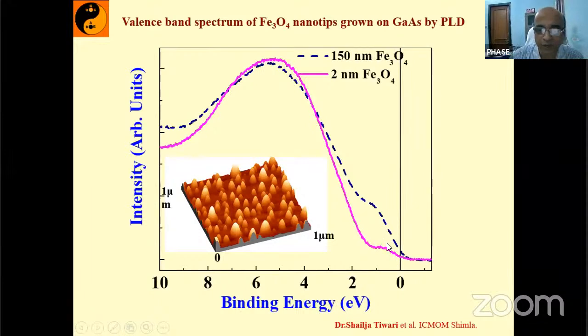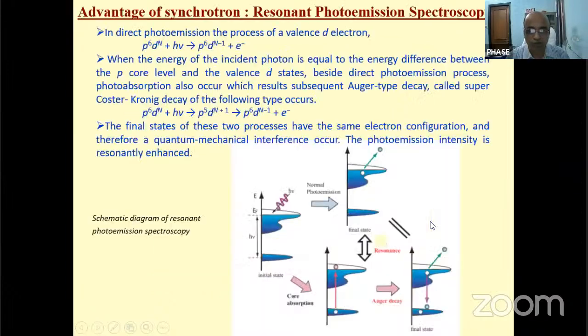So, same material with different shape. One is a thin film and one is a nanoparticle. You will see that near the Fermi energy, basically the change is in the density of states. And because of that density of states, the electronic structure also changes. One can do the theoretical calculation and find out what the changes are once you go from 150 nanometer to 2 nanometer. That kind of problems also one can do.